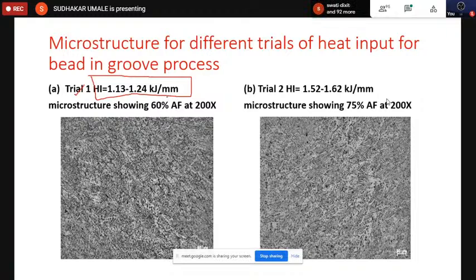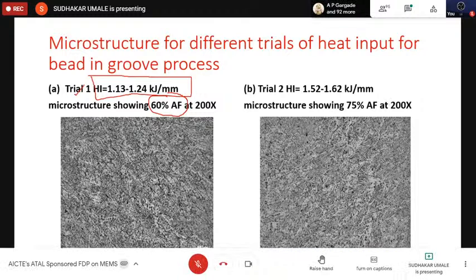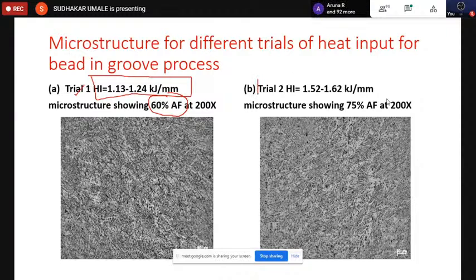Here is my volume fraction of AF, meaning acicular ferrite, and this is the microstructure at 200 times magnification. Just observe that I am getting 60% acicular ferrite. In this 100% microstructure, I am getting 60%. What is my aim? To get 100% acicular ferrite, but it is not obtained. It contains some microferrite and many other microstructures. Pearlite may be present, martensite may be present. Now observe my second trial. I have changed my current, voltage, and speed. During that period, my heat input is larger, and I am getting 75%.